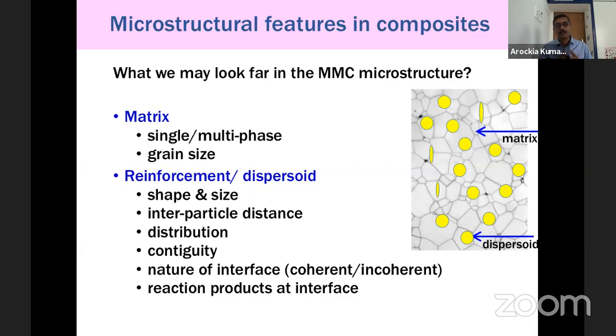Okay, so your mechanical engineers, you might have heard about ceramic matrix composites. In order to process high speed steel or very hard materials, we are using cermets. So cermet is nothing but a ceramic matrix composite, a ceramic metal composite, where in a cobalt metal, very hard tungsten carbide particles are embedded. But if you see the fraction of these particles, it used to be around 90%. So when you put 90% particles, there is a good chance that one tungsten carbide particle touches the other tungsten carbide particles. So the fraction of this shared interface is called contiguity, and this also determines the mechanical property of the composite.